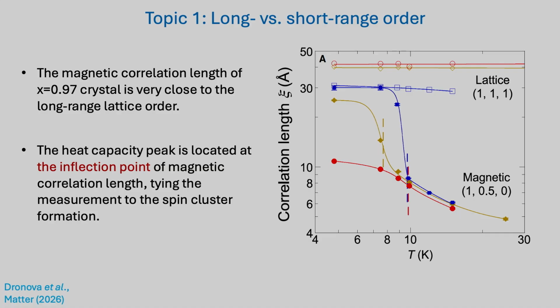Right. So this is actually the huge difference between your clean limit sample and the spin glass related sample. So now we can also study the correlation lengths. The correlation lengths of these orders at the magnetic peak, compared with the lattice correlation lengths: my x equal to 1 sample quickly saturated and becomes the same as the lattice correlation. However, the 0.97 sample has a long range correlation, but the value of the correlation length is slightly lower than what you have at the lattice. However, for the disorder sample, you never develop long range.